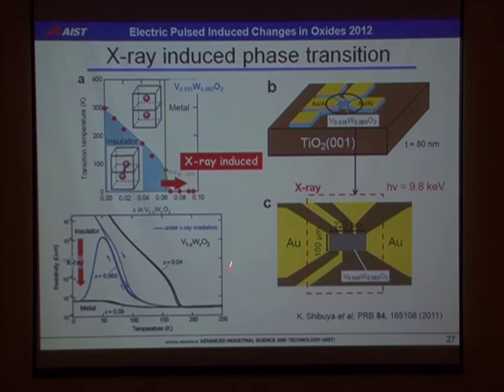So we observed persistent phase transition at low temperature using X-ray. In this case, we utilize this electron-doped VO2, which is very close to the metal-insulator boundary. The original state is this gray line, and by irradiation of X-ray, we can observe this blue line. So the conductivity reaches that of metallic VO2.